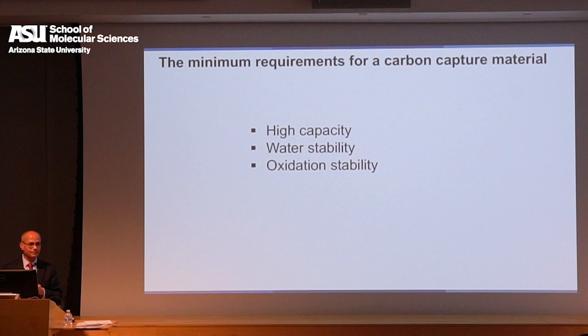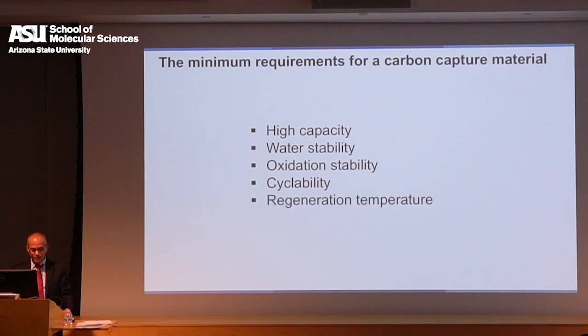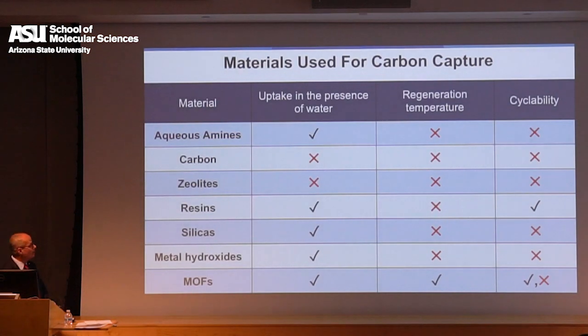Oxidation stability, because you have oxygen around and you're heating the material to remove the CO2. The oxidation of amines and the oxidation of the framework is very important. Cyclability. You need to be able to cycle many, many times, hundreds of thousands of cycles. And you need to have the right regeneration temperature. You need to be able to heat your material not to hundreds of degrees Celsius, but to something more reasonable to lower the energy requirements.